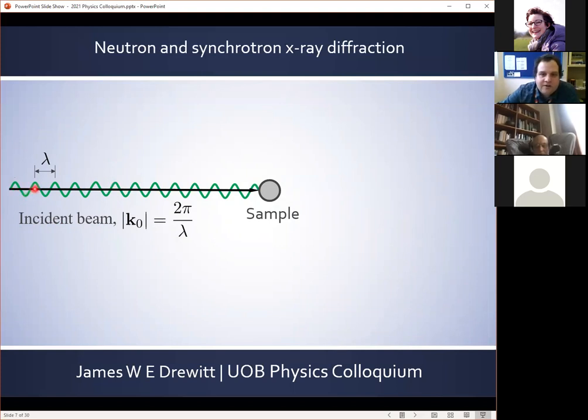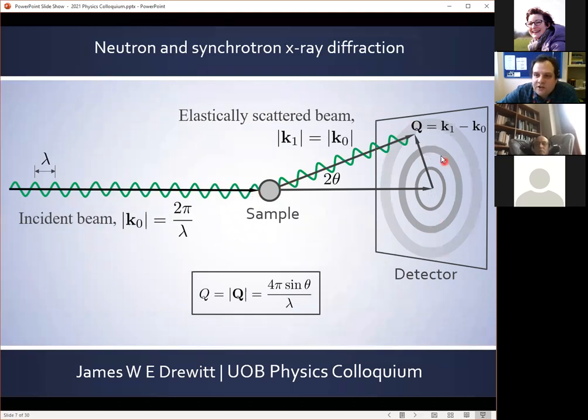So here we have an incident beam of either synchrotron X-rays or neutrons, where the magnitude of the incident wave vector is 2π upon λ, where λ is the wavelength of our incident X-ray or neutron. And typically the wavelength of an X-ray or a neutron is comparable to the atomic spacings in a material. So the incident X-ray or neutron scatters from our sample, and we can measure a two-dimensional diffraction pattern as a function of our elastic scattering vector Q, which is defined as 4π divided by the wavelength multiplied by the sine of one half of the scattering angle.